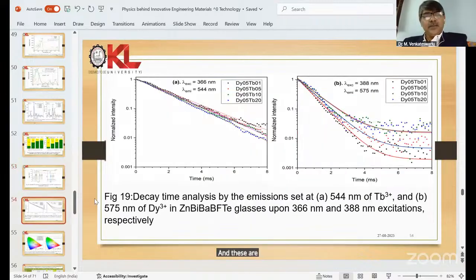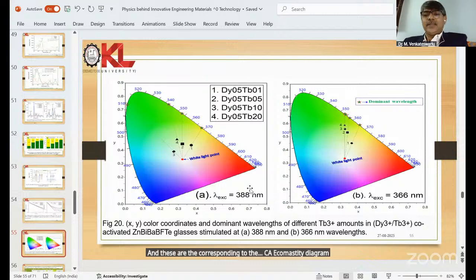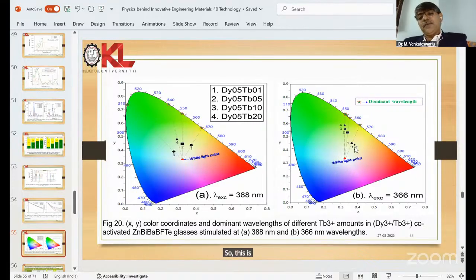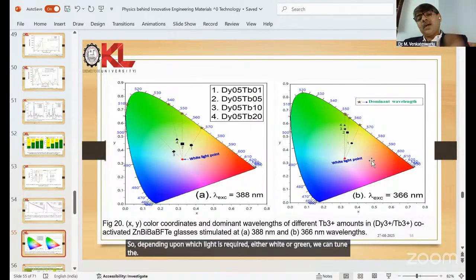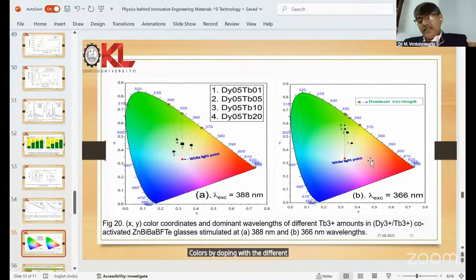And these are the corresponding decay curves. And these are the corresponding CIE chromaticity diagram. At 388 nanometers, you can observe carefully, this is the white light, and it gradually shifts from the white light region to the green color. Sample 2 is the maximum, and the remaining 1, 2, 3 are near to the white color. Similarly, at 366 nanometers wavelength, it shifts from white light to complete green color. So depending upon which light is required, either white or green, we can tune the colors by doping with different concentrations of the rare earth ions.